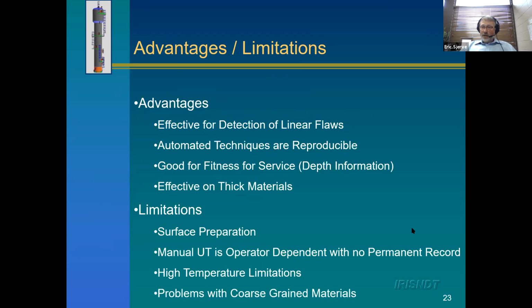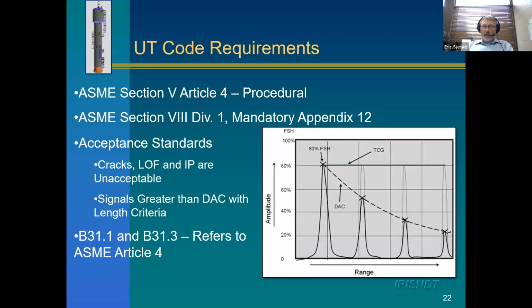Okay, so we've got a question here. The question is, what do signals greater than DAC mean? So with that, what we're doing is these lines here are from the calibration block. When we're doing an inspection, we have a certain thickness of plate or of weld, and we go off to the code, and the code tells us how big the side drilled holes are. The side drilled holes are how we set the sensitivity of the ultrasonic system. So maybe they're 3mm side drilled holes for a plate that's 1/2 inch thickness.